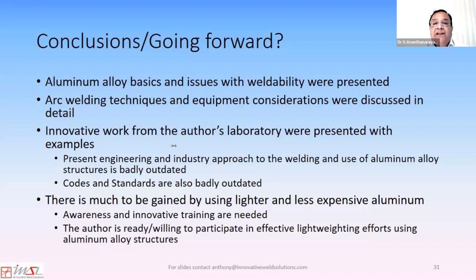How many times can we repair weld joints? Oh, wow. I think you are talking about aluminum. Aluminum loses most of its strength even after one welding effort. As I showed you, it can lose more than half the strength or the hardness in the heat affected zone. If you keep welding it to do repair welding, you probably don't have much mechanical strength left. And you're also probably metallurgically affecting it. Any effect of cold work or any effect of heat treatment that you've had on the alloy would be lost.